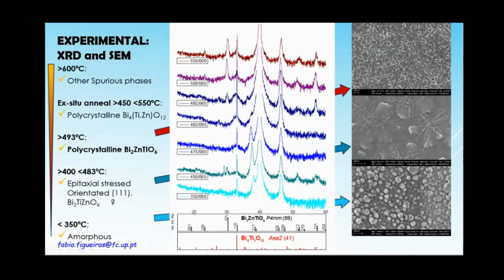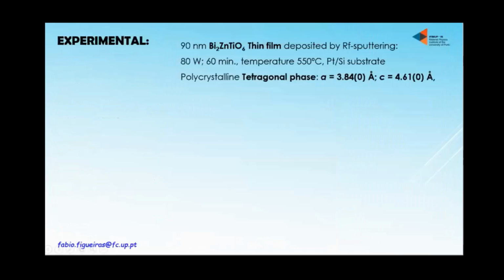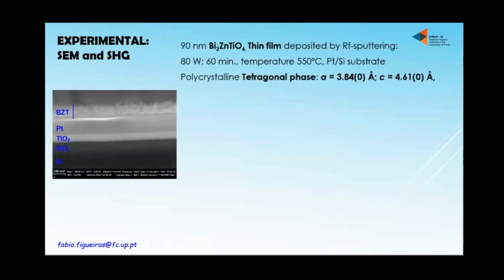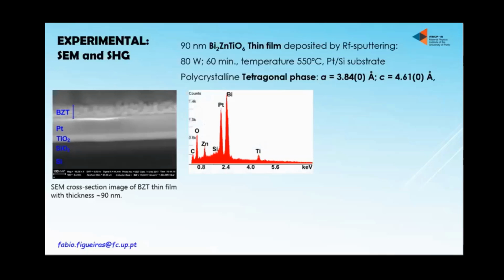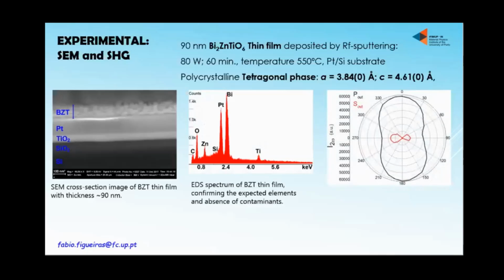So I will now focus on: do we really have this material that is not so easy to stabilize as a bulk form, only in high pressure? So we made lots of studies in terms of electron microscopy, checking the material composition, and in terms of second harmonic generation, to understand if the real material was really ferroelectric or at least non-centrosymmetric. High success in these measurements proves that the material has a tetragonal phase, a really big difference between C and A parameters, promising a high ferroelectricity.